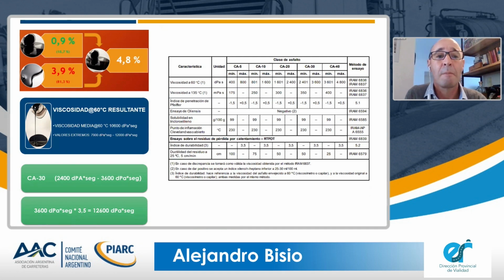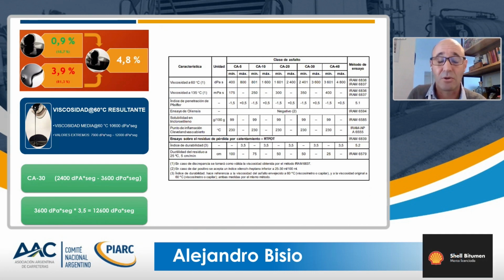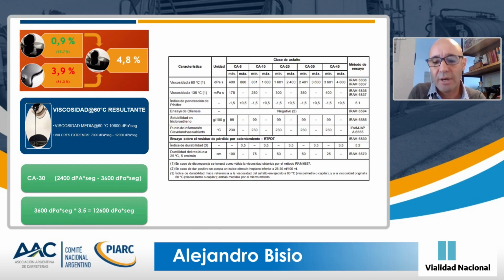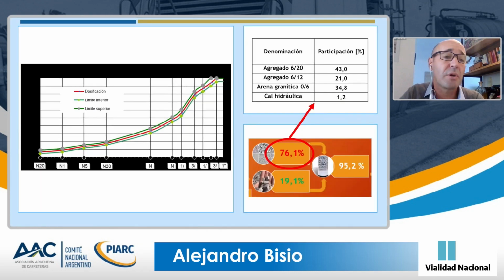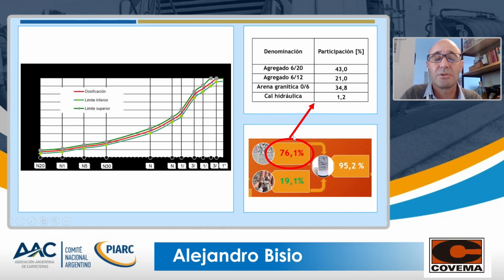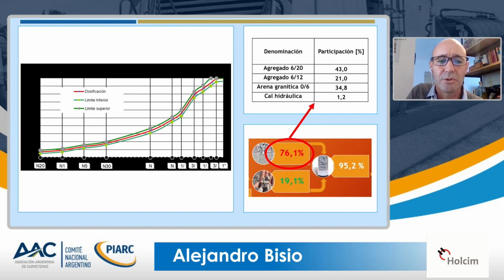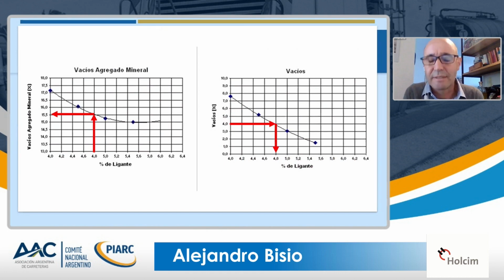In certain specific cases, in order not to exceed this limit viscosity value, we used one or two lower grade binders, maybe CA20 or 10, but in general we used the same grade of virgin binder. As to the granular structure, 76% of the virgin asphalt came from 2 coarse aggregates, 1 fraction of fine aggregate, and 1.2% lime because of durability issues.